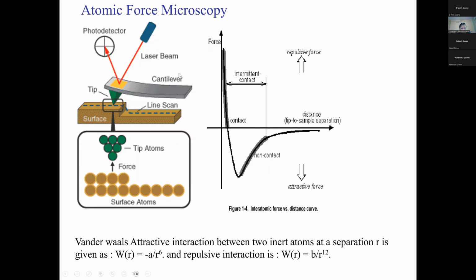But the power of this is small, a very fine laser, especially a red light laser, so that normal visible light can be avoided. You can use ultraviolet lasers also, but it's better to avoid heating. So nowadays, even 680 or above 1000 nanometer lasers are available. No heating effect will be there, and this will be reflected. So it's a lamp and scale arrangement like a galvanometer in your school, which you have studied. Here the displacements are nanometers, but because of this lamp and scale arrangement, the photodetector signal is amplified heavily, and the top and bottom height signal will come.